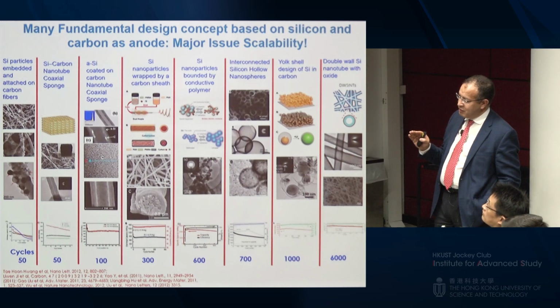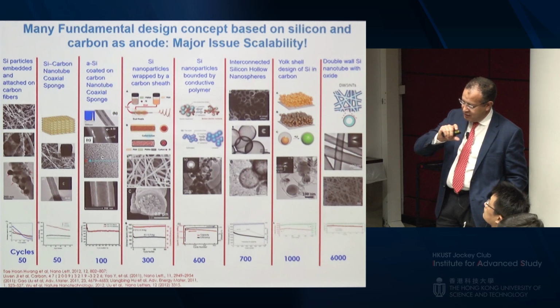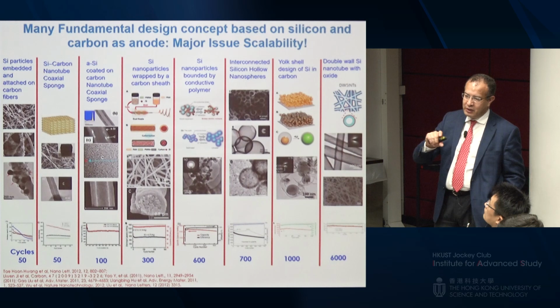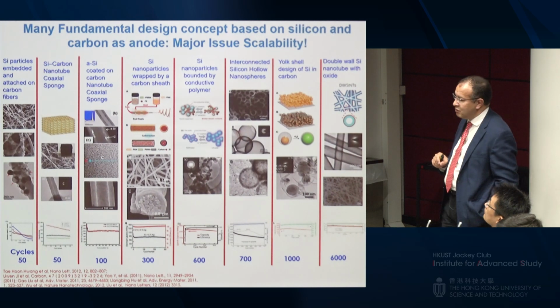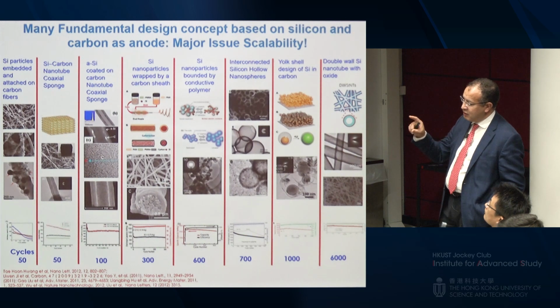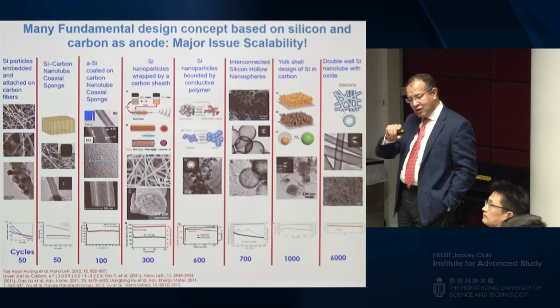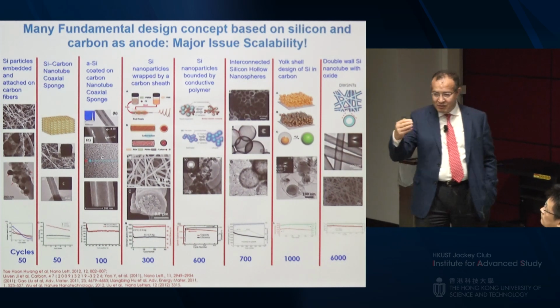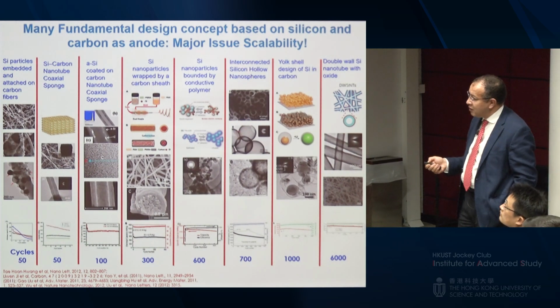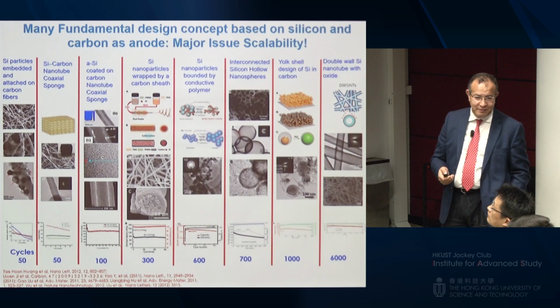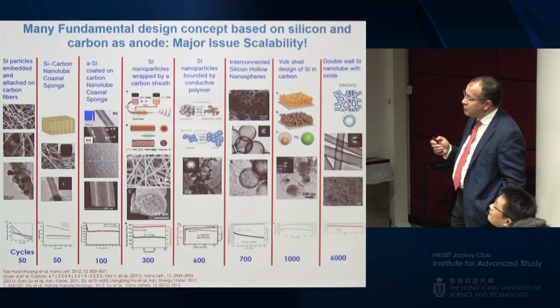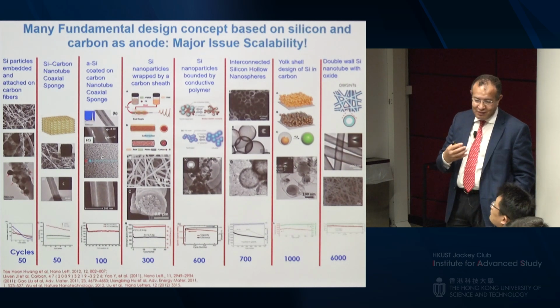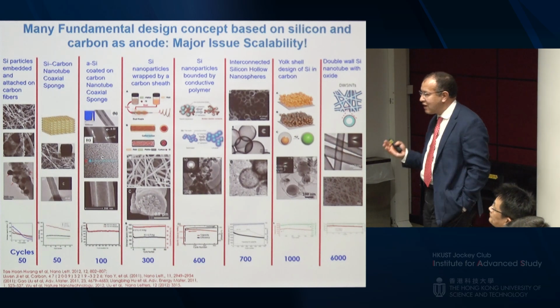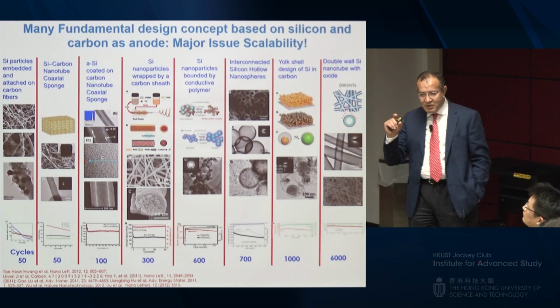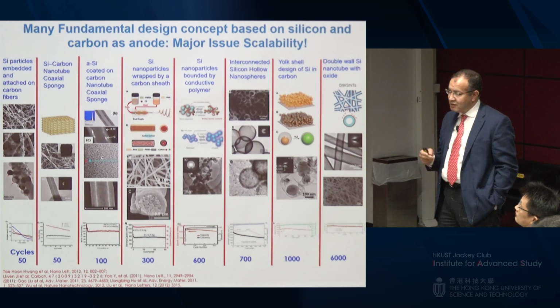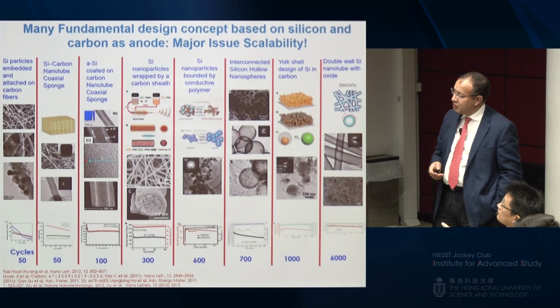If you guys are doing work on batteries, you have to set up the conditions of testing. It's really important if you want to compare apples to apples. That's what we did at DOE. For all the programs funded by DOE on silicon, we have clear conditions of how you make the electrode and how you test it, so you can test apples to apples. The only thing in common among all of these is that they are not scalable. And that's the reason why you see most of the industry just mixing 90% graphite with maybe 5% silicon to get maybe a 20% increase in the energy density. That's what Panasonic and others do, and the Korean and Chinese.